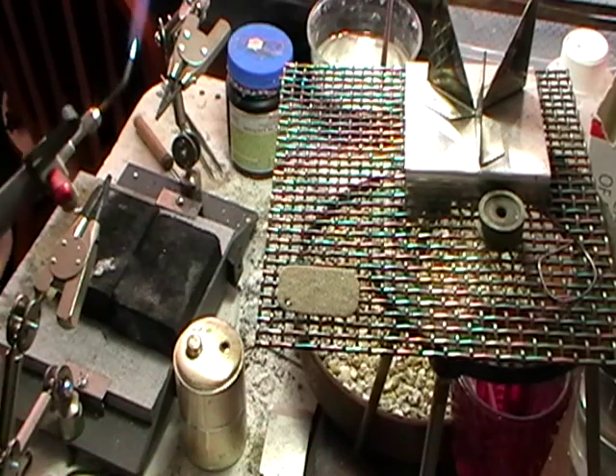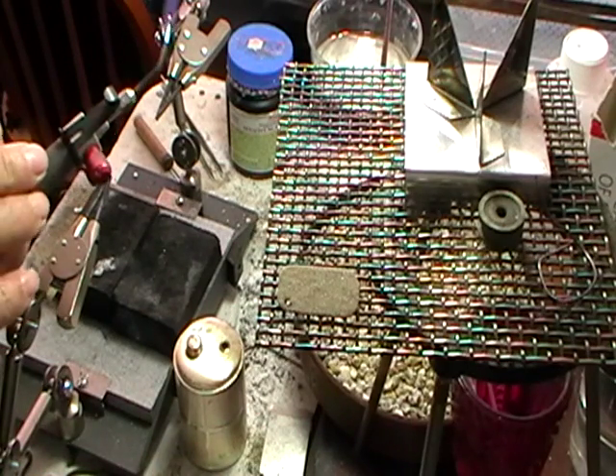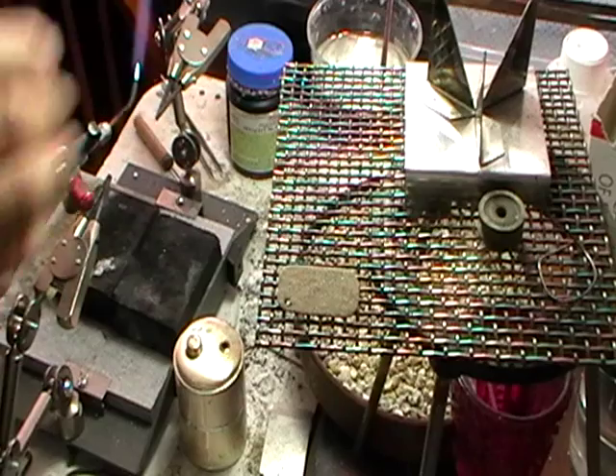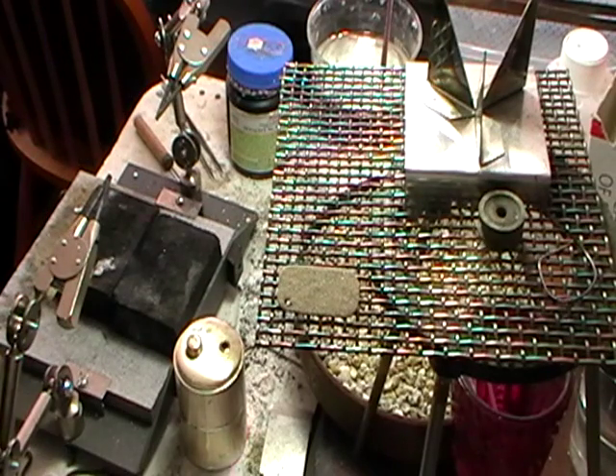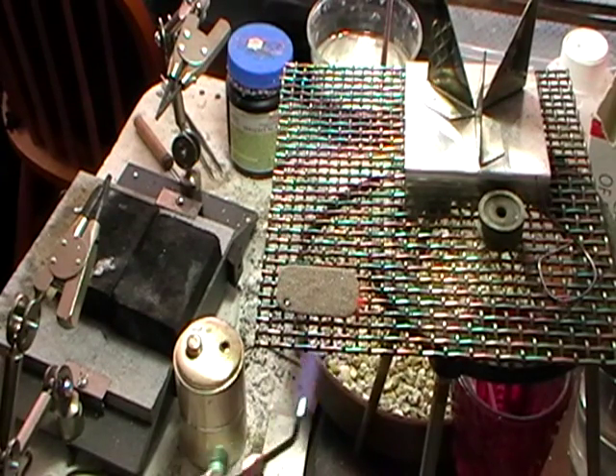Okay, I'm going to fire this from underneath. I've got my Smith's Mini Torch with a number 7 tip and a fairly big flame. And I'm about 75 mil away, just brushing this from end to end. And you'll see the glass powder change as it starts to melt. And basically we're just melting the glass powder into the metal.